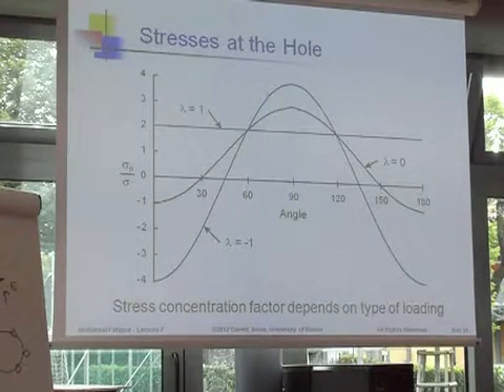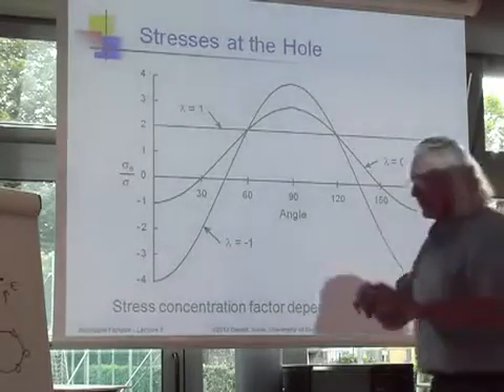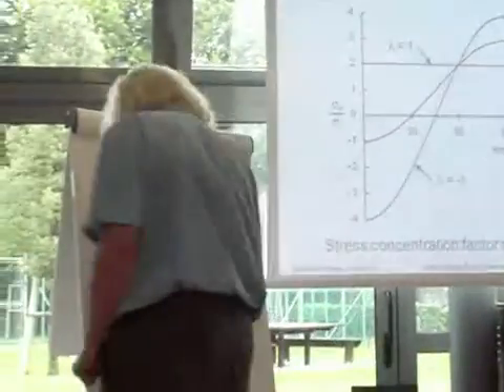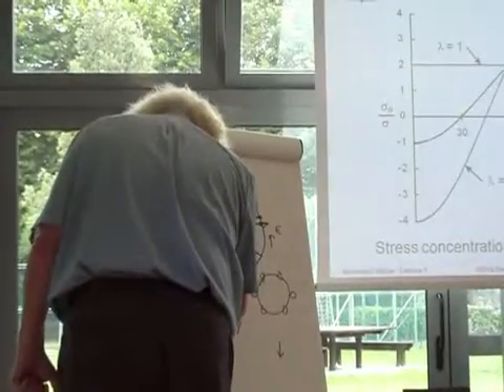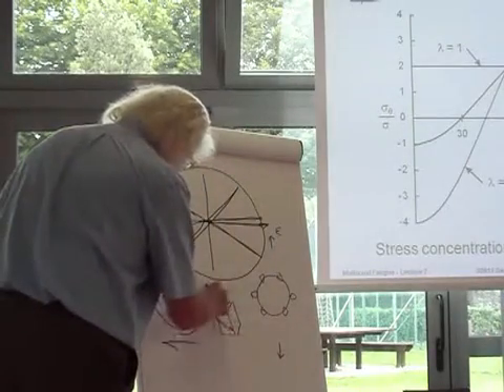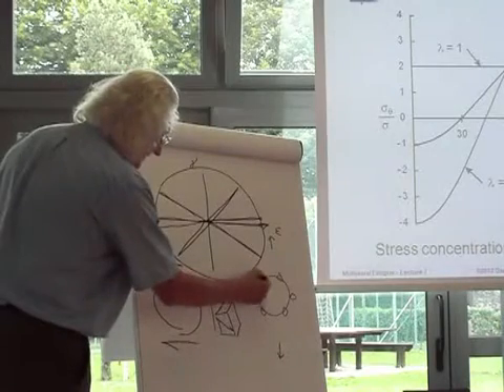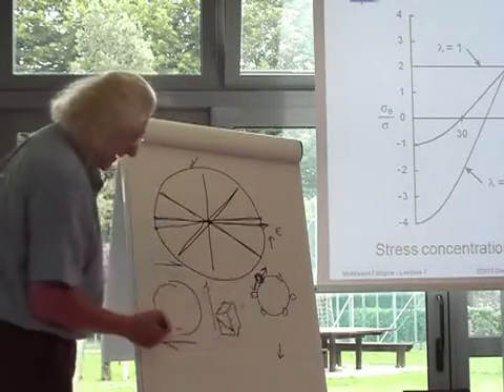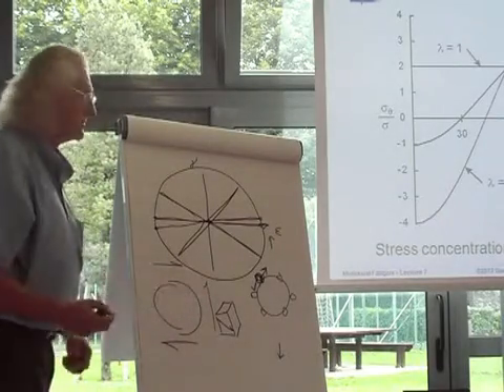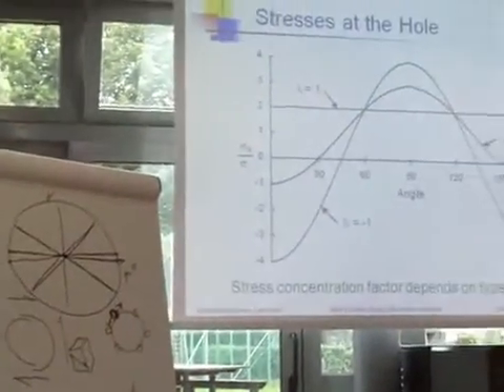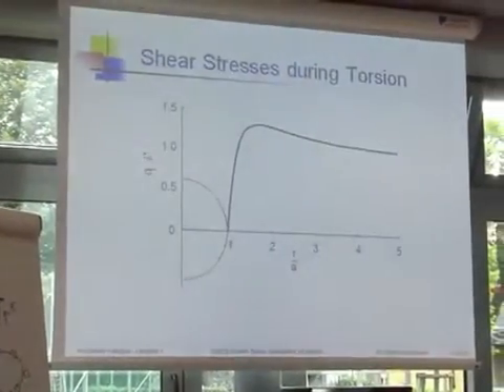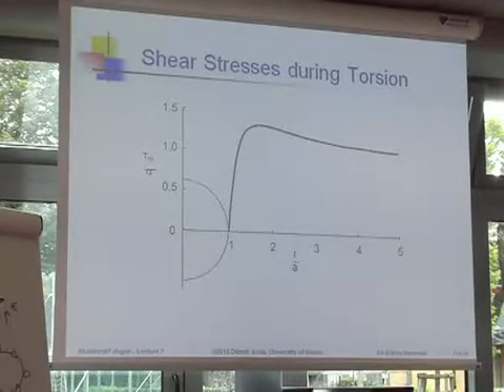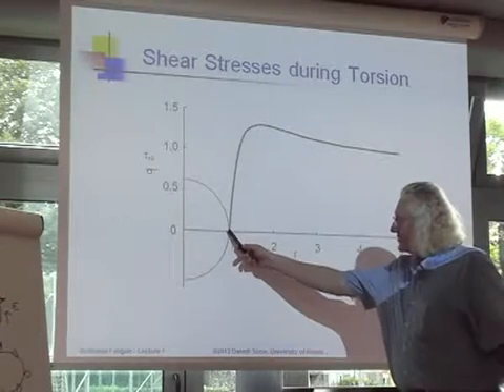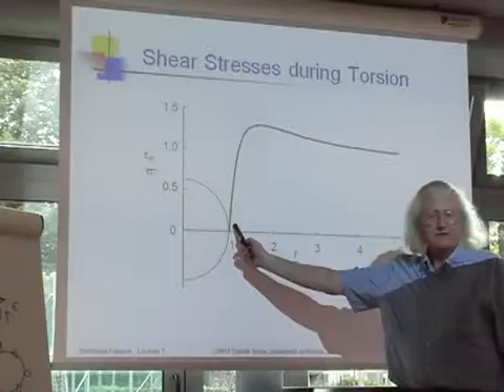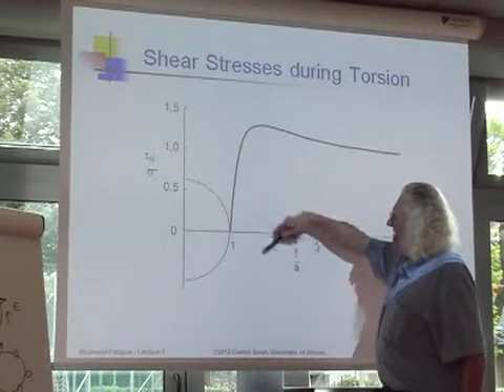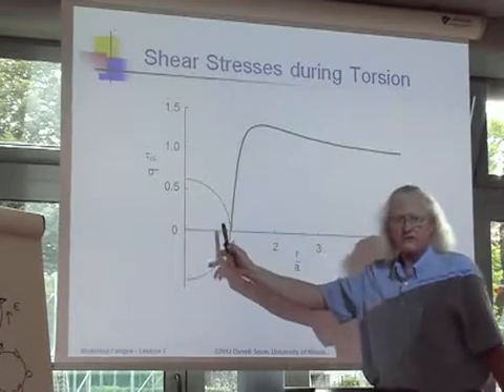The other thing is, what if I twisted the hole? You know, what if I applied pure torsion to a hole? Okay. And instead of looking at what the tensile stress is here, I look at the shear stresses around the edge of the hole. Well, if you do that, there's the shear stresses around the edge of a hole, which is loaded in torsion. And if you look right at the edge, you'll see that the shear stresses are 0. And they peak up at a distance of about 1.3 times whatever the radius is.